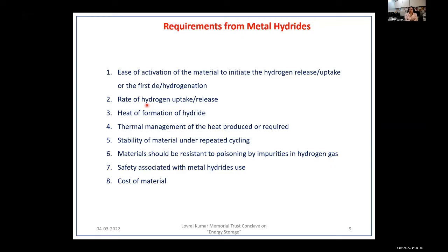Now, what exactly do we look at when we talk about metal hydrides? They should be easier to activate, meaning the first hydrogenation-dehydrogenation cycle, the uptake and release of hydrogen, should be easier. It should not require very high temperatures and pressures. The uptake and release should be faster, so the rate should be higher. They should have a reasonable heat of formation of hydrides. This becomes very important for large-scale solid-state hydrogen storage systems, because one process is exothermic and the other is endothermic. A lot of heat needs to be supplied and taken out, so thermal management becomes important. Metal hydrides with an optimum heat of formation, somewhere around 30 kilojoule per mole, would be very good to operate with.